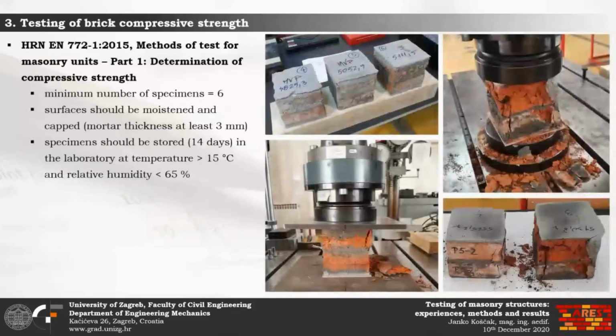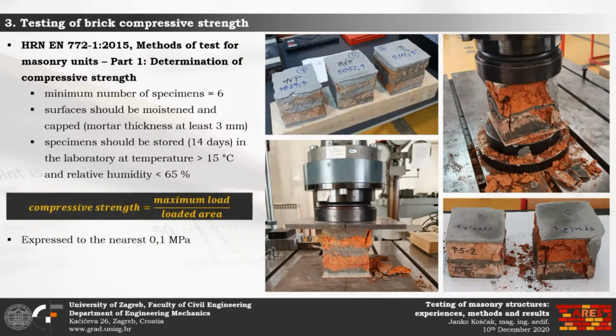Testing of brick compressive strength is shown next. In the laboratory, we performed this test according to European standard methods of test for masonry units, and according to the standard, a minimum number of tested specimens should be 6. The surfaces should be moistened and capped with mortar at least 3 mm thick, and specimens should be stored for at least 14 days in a controlled environment. Of course, the compressive strength is then calculated as the maximum load applied over the loaded area and should be expressed to the nearest 0.1 megapascal.